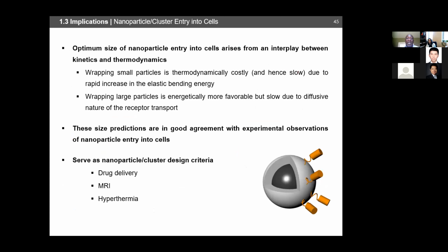And the optimum size for nanoparticle entry into the cells arises from the interplay between kinetics and thermodynamics. The wrapping times for small particles is thermodynamically costly and hence slow due to the rapid increase in elastic bending energy. And then the wrapping of large particles is energetically more favorable, but slow due to the diffusive nature of the receptor transport. And so these kinds of insights are actually consistent with our observations in both in vivo and in vitro experiments. And they provide the basis for developing drugs and for doing imaging, as I will show in the next section.